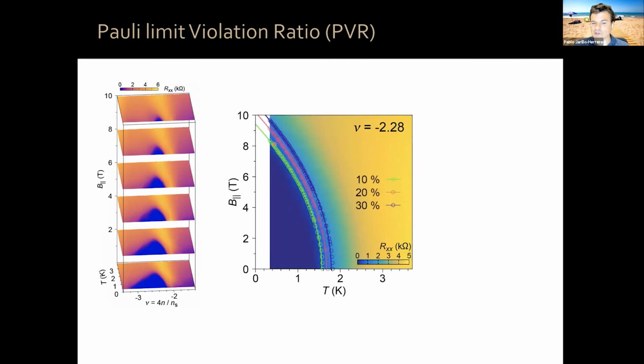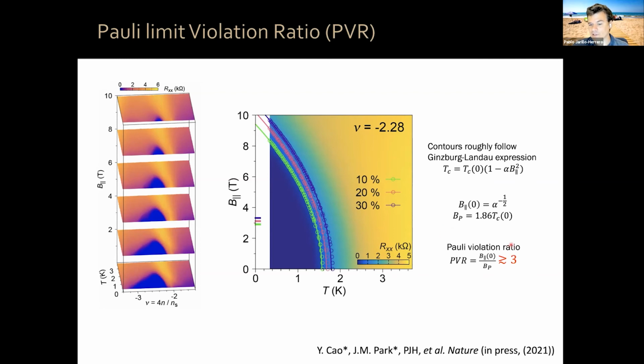We can take any threshold that we want for superconductivity, 10%, 20%, 30% of the normal state resistance. It doesn't matter, all the same. These are parabolic equal resistance contours. You can then extract the Pauli limit according to whatever ratio you want. As you can see, our system superconducts at much, much higher ratios. In fact, the Pauli violation ratio is in excess of 3 for the system. So this actually, this is about to appear.